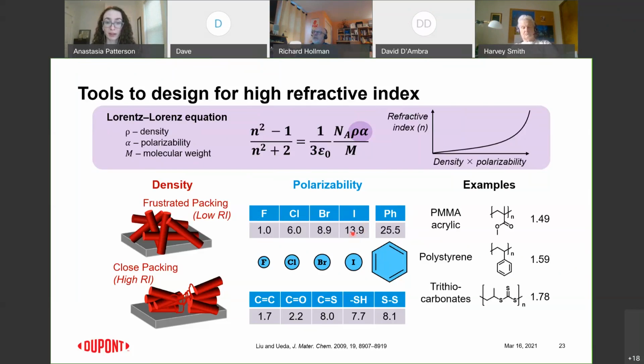So for some examples, PMMA acrylics are the sheets of plastic you see between you and the cashier these days. Its refractive index is around 1.5 in the visible spectrum. But if we replace this sort of very dipolar group with an aromatic group, then we can get a higher refractive index because those aromatic electrons are all very polarizable, very delocalized. And so that increases the refractive index to around 1.6. And if we go to the extreme and start replacing different atoms with larger atoms like sulfur, that boosts the refractive index even more to around 1.8, which is very high for organic materials.